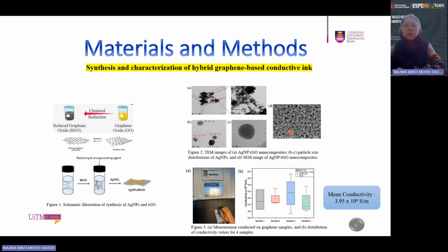And from this SEM image, it can be seen that there is a good attachment between graphene and silver particles, which contributes to the high conductivity of the material. The conductivity of the material has also been measured by using a 4-point probe system here, where the mean conductivity achieved is 3.95 times 10 to the power of 6 Siemens per meter.